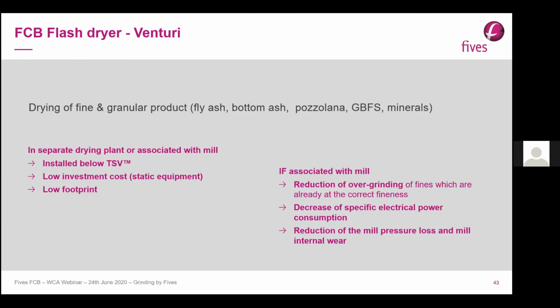The results are a reduction of overgrinding of fines which are already at the correct fineness. It's the first selection of fine product before coming into the mill. It decreases the specific electrical power with a low pressure drop of the mill. And it also decreases the mill internal wear due to lower moisture in the mill.